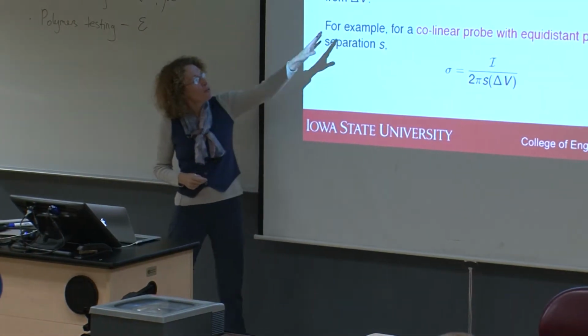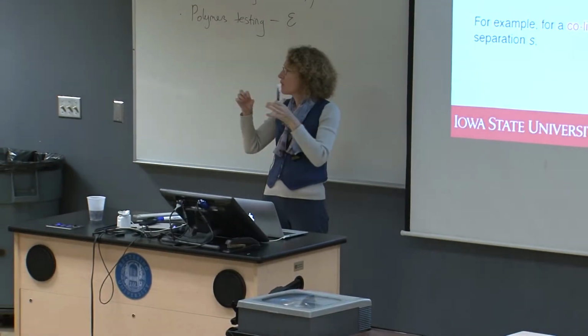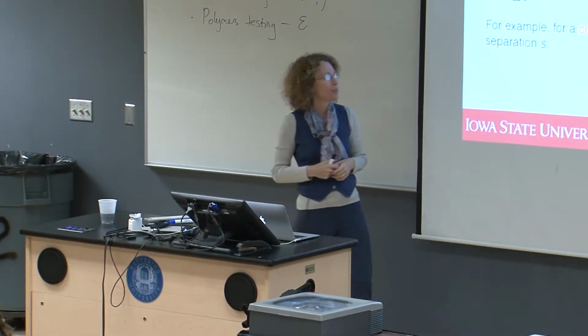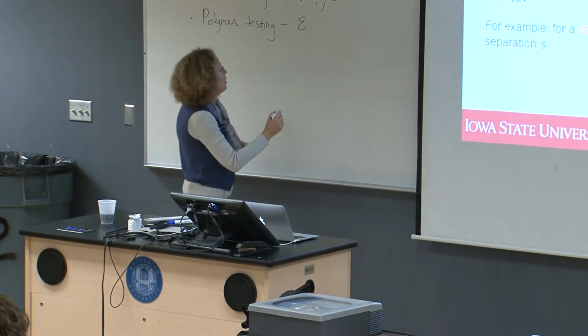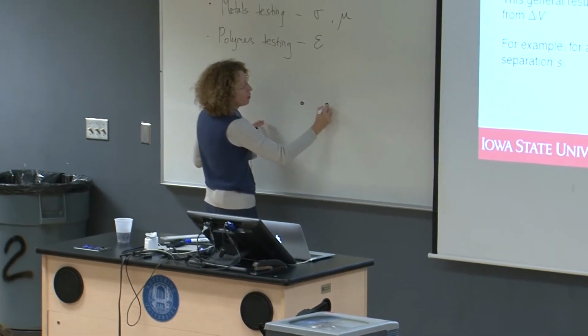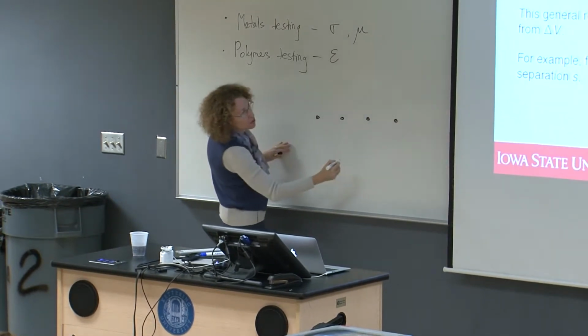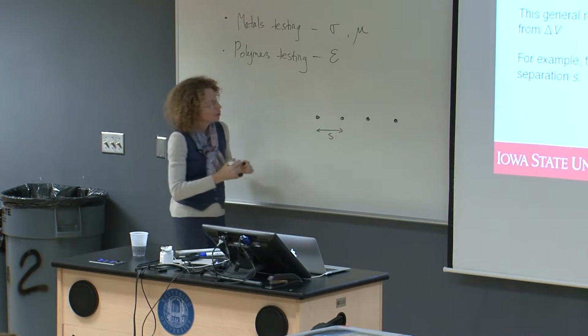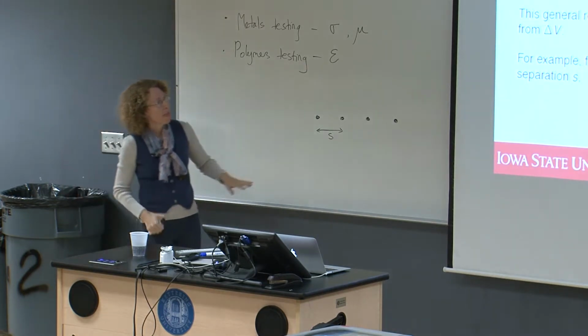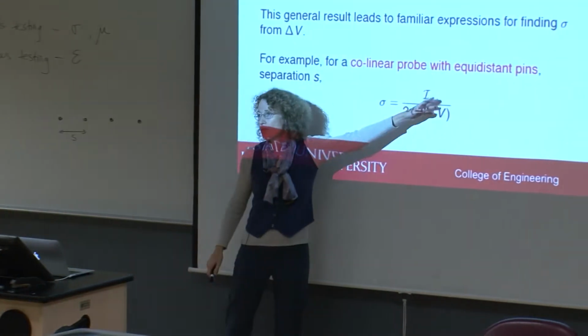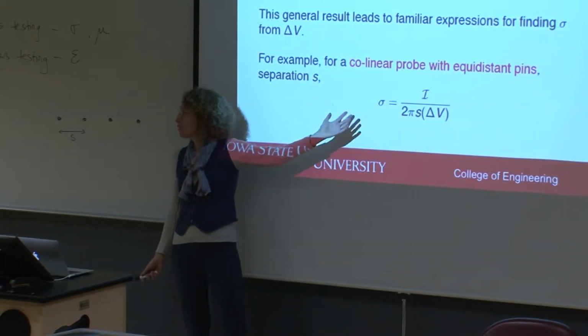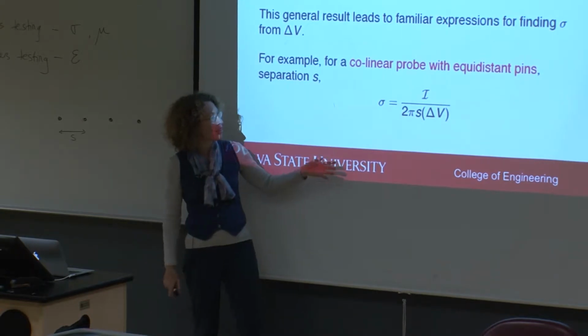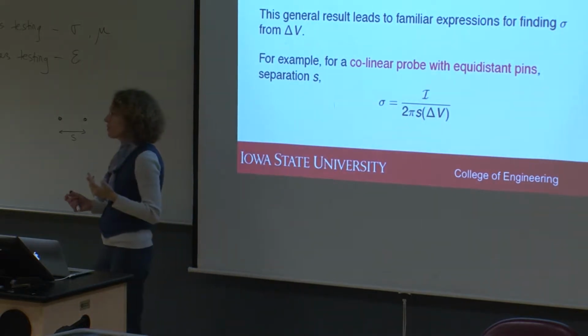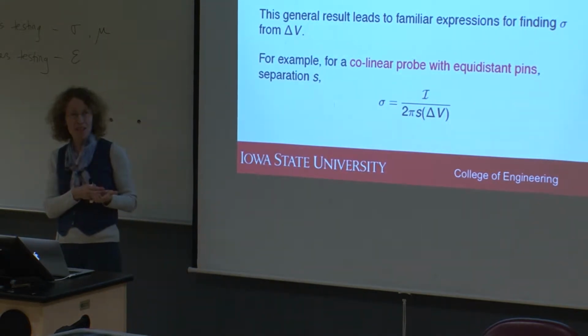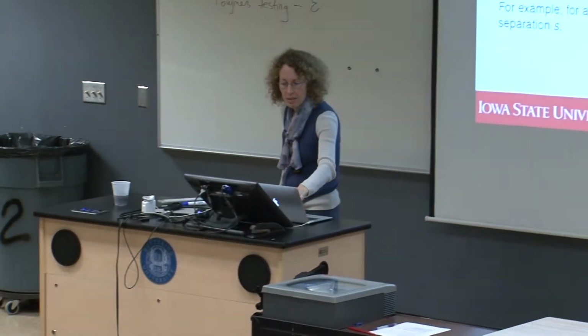So what that means then, you can play around with these distances now. The distances between the different pins, you put in some values there. And if you have a collinear probe, which would be like this, with an equal separation between those, which I've called S here, then you can express your conductivity in this really simple formula. It's a back of the envelope type of formula. We could even do that in our head. So this is the distance, this is the potential drop, the current, and you've got the conductivity very simply like that. There's not many testing approaches that are as simple as this.